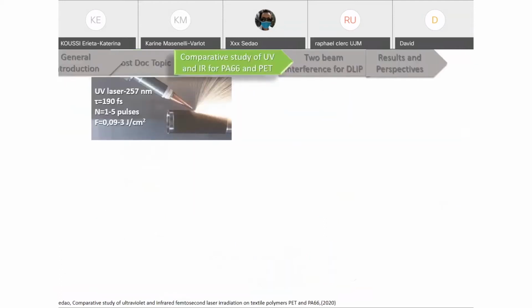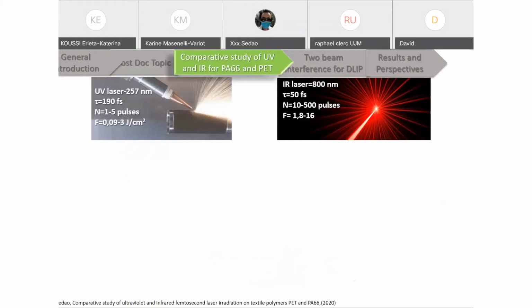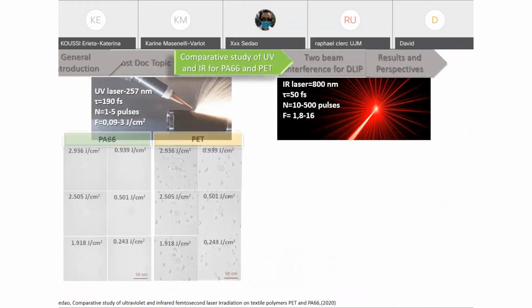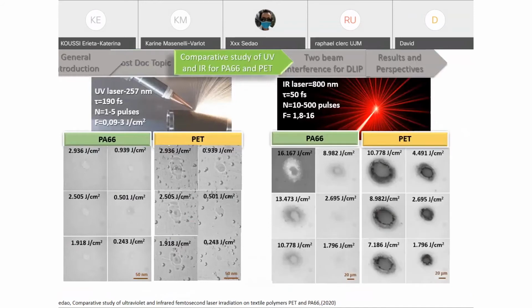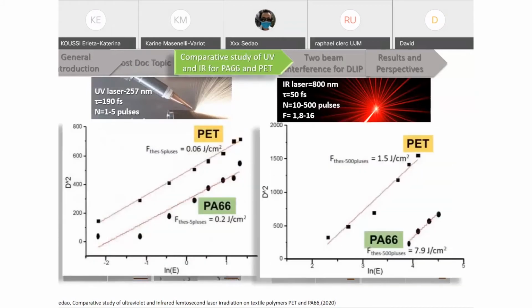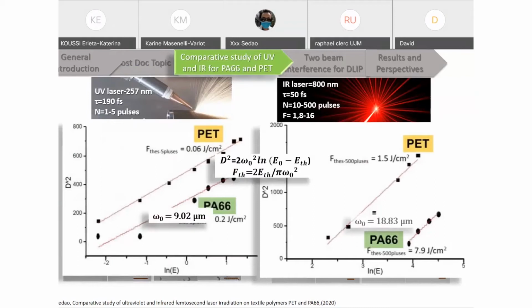So the first experiments of this project started by conducting a comparative study for both laser beams, UV and IR, and for both polymers. By irradiating, we have thus ablated the surface by forming craters, which were continuously observed by optical microscope, as you can see, and the diameter of its impact was measured. By measuring the diameter of each impact, we were able to plot the graph, and doing the linear fitting and comparing the terms with this formula, we can define the waist for each beam radius. For UV, it's 9.02, and for IR, it's 18.83 micrometers.